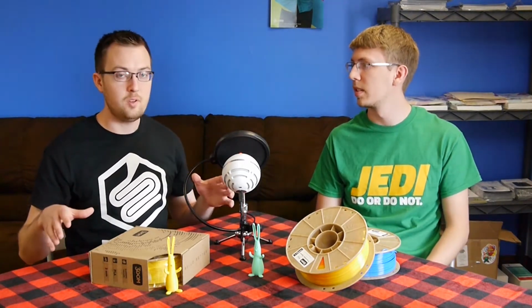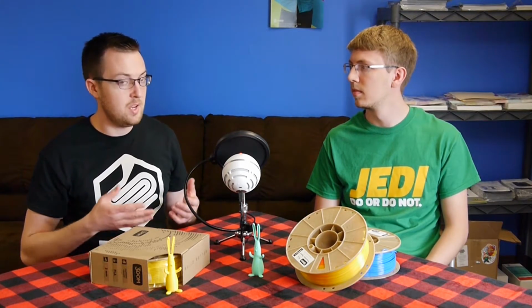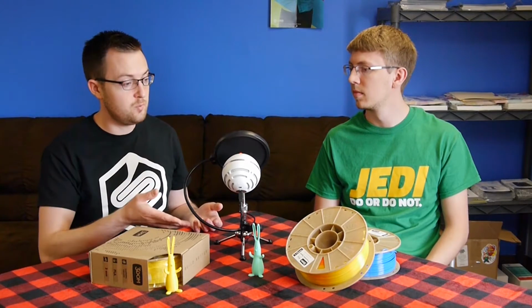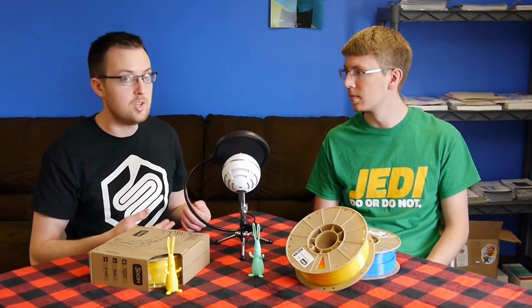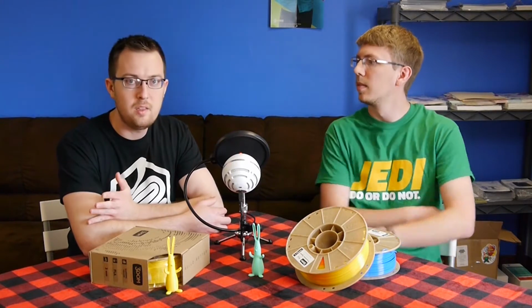Basically, with a landfill, they end up sealing it up, and they don't add any moisture to it. They try and take as much air out of it as possible, so it doesn't break down like industrial compost would. So you put the spool in an industrial compost situation, high heat, high humidity, and the spool will break down. It's about 1 to 3 months, depending on the temperature.